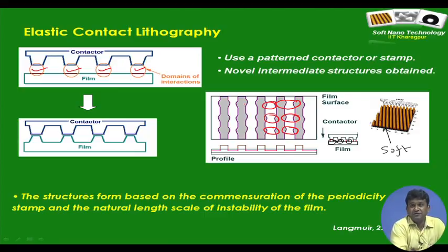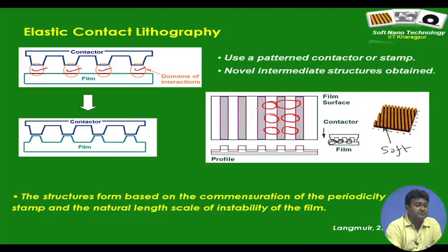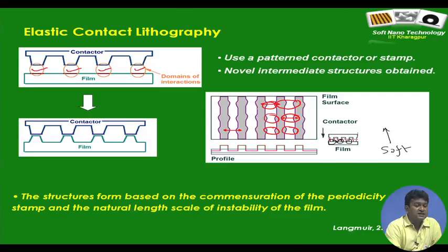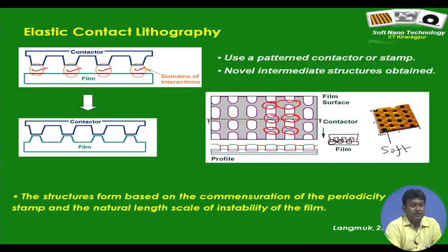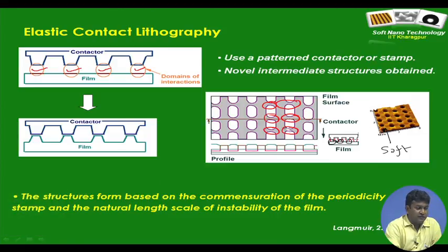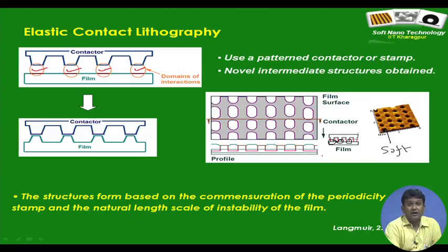When they are in the range of active van der Waals interaction, because they are after all interacting in air, so there is no chance of any repulsion, these undulations simply join up, and therefore what it forms is an array of holes, which in fact you have seen in the context of dewetting. There was a pattern directed dewetting video a few lectures back where we used this identical substrate.